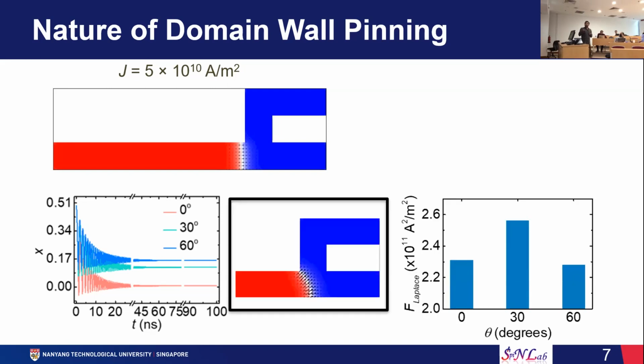Now, taking one of the images of this motion, we take the radius of curvature of this surface, and that is needed to calculate the Laplace force. The Laplace force is basically an indication of the pinning strength. In the variation of the Laplace force with theta, you see that the Laplace force increases from 0 degrees to 30 degrees, and finally it decreases again.